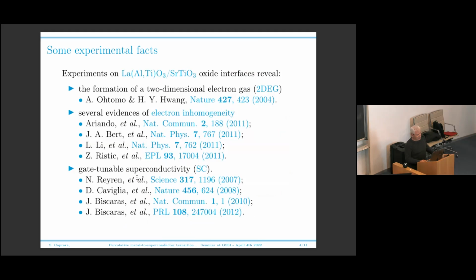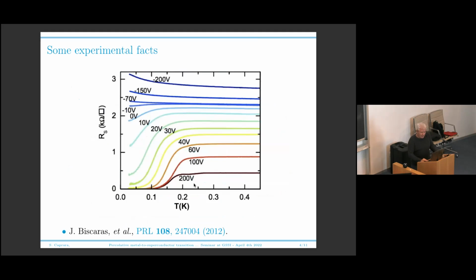This is one description. So what is interesting here is the occurrence of superconductivity. This was the first example of superconductivity that can be induced by gating, which is striking by itself. And this is a typical situation. Here you have a large positive gating, and this is the resistance as a function of temperature. You start from a metallic state here, you lower the temperature, and your resistance goes to zero with a very, very long tail. This is a very wide transition, which cannot possibly be described by a standard fluctuational mechanism, like, for instance, paraconductivity. This is a very large, very broad superconducting transition.